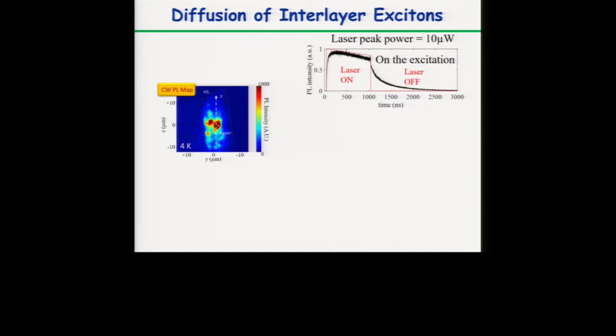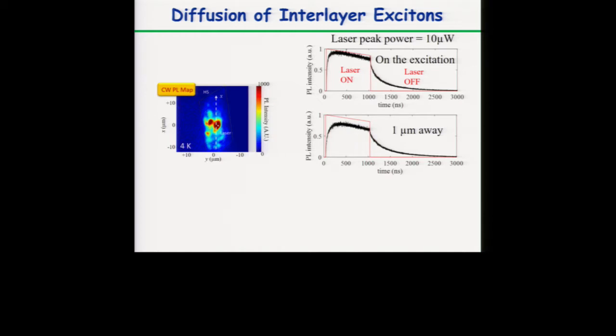On the excitation spot, we can see the laser is this red plot, right? So the laser is on or the laser is off. For the collection on the same spot for the interlayer exciton, it takes some time to get to the peak right after the laser gets on, and it takes longer for it to die after the excitation is off, right? So this is this long lifetime. But if we go 1 micrometer away from the excitation, first the intensity is lower, right? Because now it has to move in space. It takes longer for it to reach a maximum compared to what it took on the laser spot. And if we go even farther away, it takes much longer for it to reach the same maximum, the same peak of intensity.